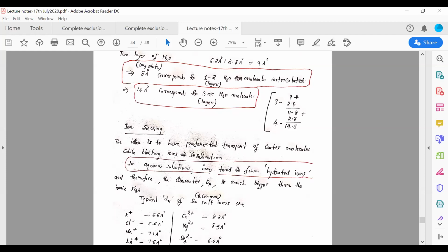You understand? So either you have to use some mechanical support from both sides, a mechanical clamp, like in normal RO systems, where the active membrane is sandwiched between two other membranes so that you don't have the expansion. You get mechanical stability. This is the major problem with this kind of laminates: mechanically they are weak, and also the spacing is larger. So now the question is, can you make it smaller?